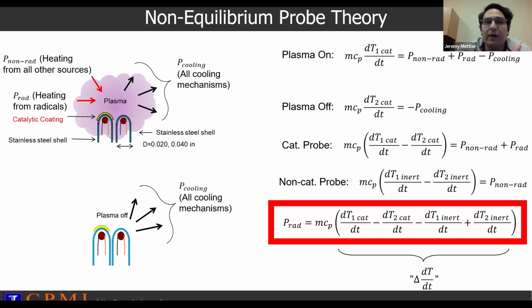And so if you consider what the system looks like as you have the plasma on and then suddenly extinguish the plasma, you can come up with a few heating and cooling terms. If you group the heating terms as radical-driven and non-radical-driven heating terms on the catalytic probe, and you assume that those extinguish rather quickly as the plasma is extinguished, which they do because all the species are very short-lived, you can come up with this relationship where you relate the slopes of the curves now, instead of just the temperature difference, the difference between the slopes of both a catalytic curve and a non-catalytic curve to this overall heating term due to radicals, which then in turn should be proportional to the density of the radicals in the vicinity of the probe. So that helps to address the shortened lifespan.